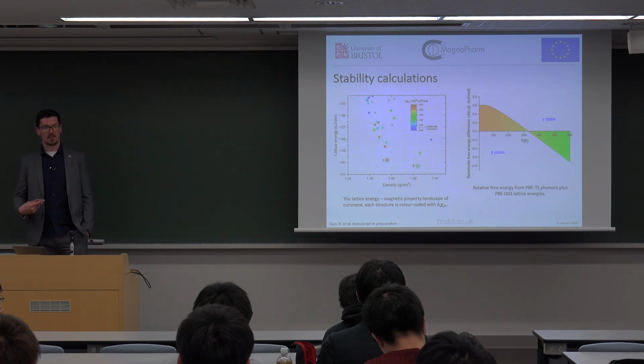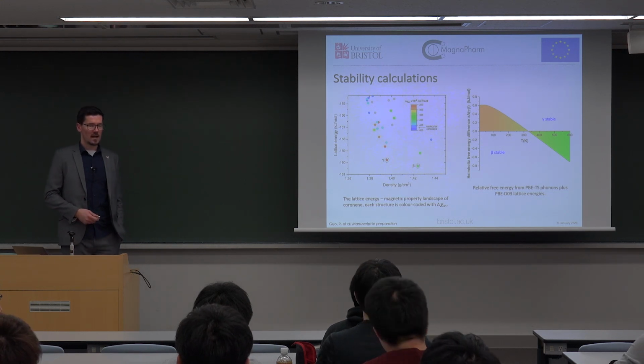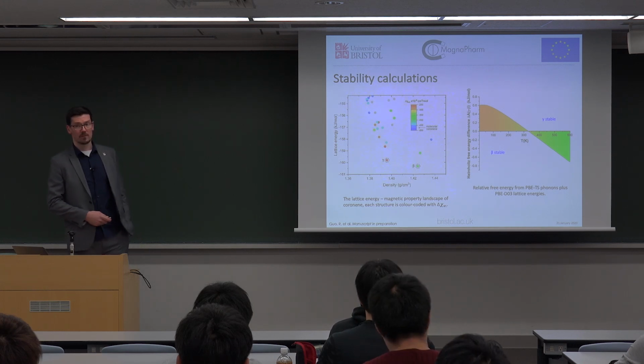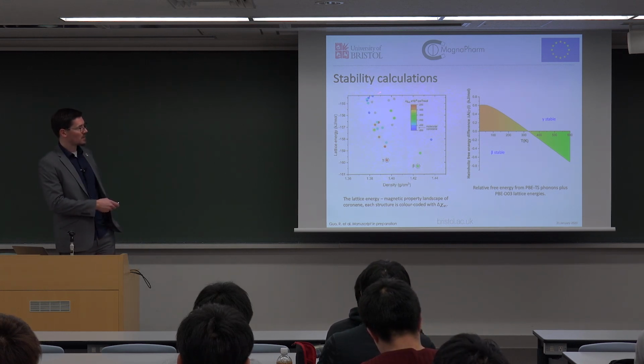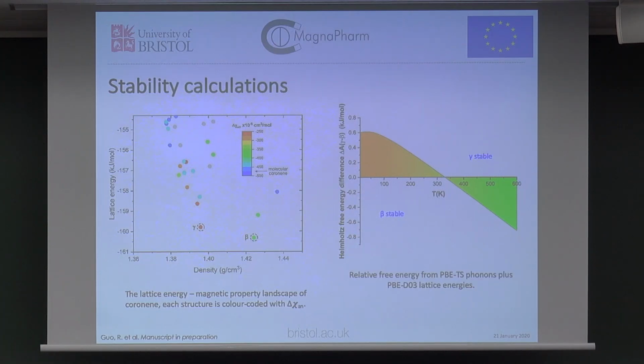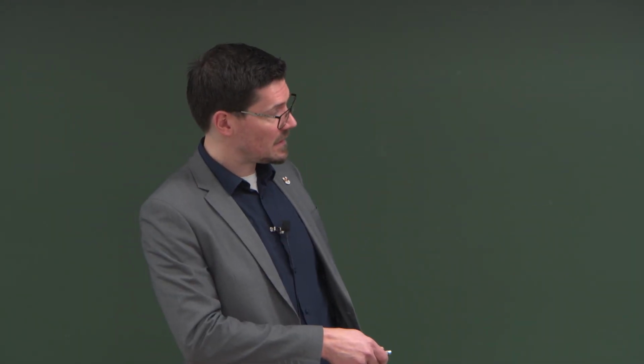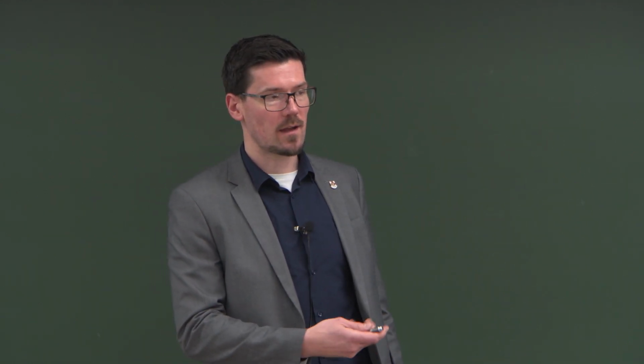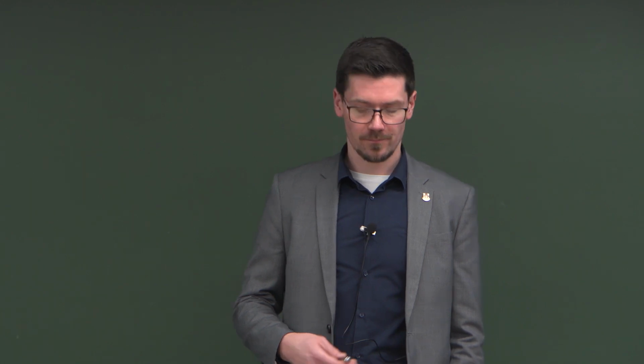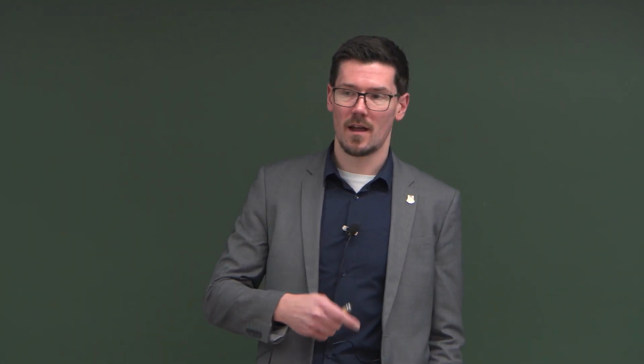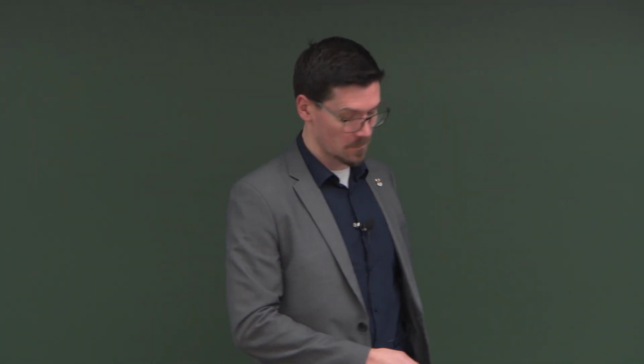Rui at UCL made some calculations on coronene. He did a crystal structure prediction on coronene after we found the second polymorph. So every one of these spots is a new energetic minimum for the coronene crystals to sit in. So each one of these is a slightly different crystal structure. And you can see at the bottom, gamma and beta are by far the lowest energy. So it makes complete sense that those are the two that we see. Surprisingly, the beta is the lowest energy. These calculations are all done at 0 Kelvin. So it looks like at 0 Kelvin, at lower temperatures, beta coronene is actually the more stable.